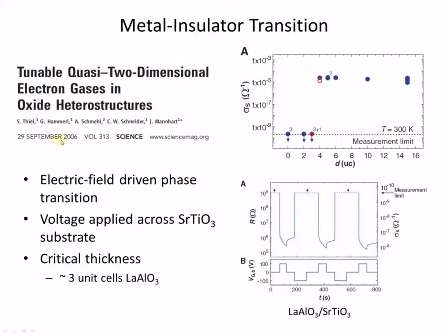In 2006, there was another group led by Jochen Mannhart at the University of Augsburg. They explored the insulator to metal transition as a function of the increasing thickness of the lanthanum aluminate layer. What they found is that if there are 0, 2, or 3 unit cells of lanthanum aluminate grown on strontium titanate, as I had indicated before, the interface was insulating.